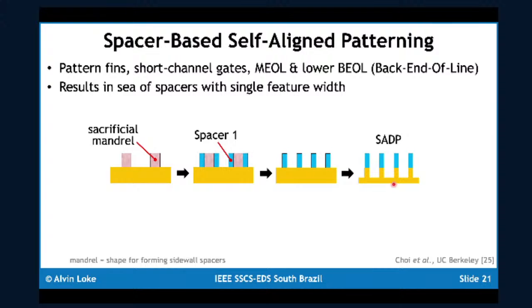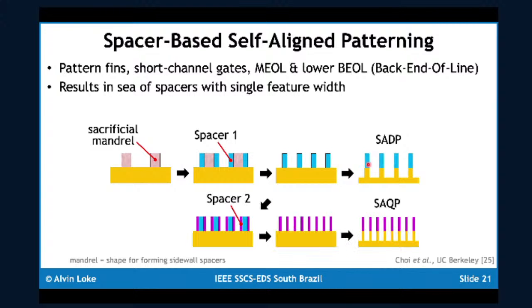This is limited to a spacer pitch of half that of the mandrel, or half of 76 nanometers, which is 38 nanometers. If you need to push further than 38 nanometers, you basically repeat this process one more time, where you use spacer 1 as your mandrel for growing a set of spacer 2s, leaving behind twice as many spacer 2s as spacer 1, or 4 times as many spacer 2s as mandrels. This technique can theoretically bring us down to 1/4 of 76 nanometers, or 19 nanometers in feature pitch. This is referred to as self-aligned quadruple patterning.